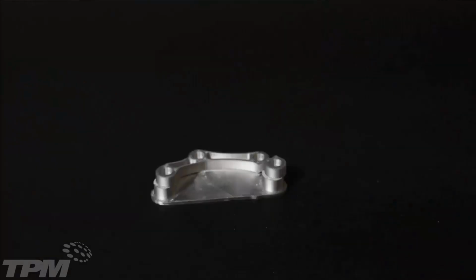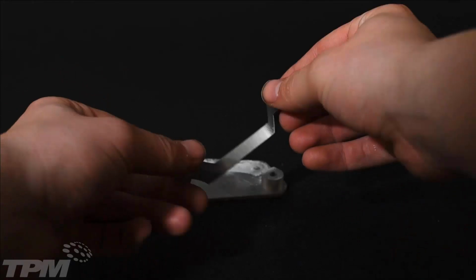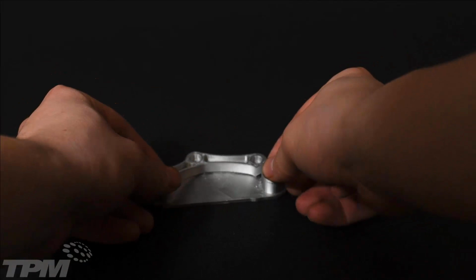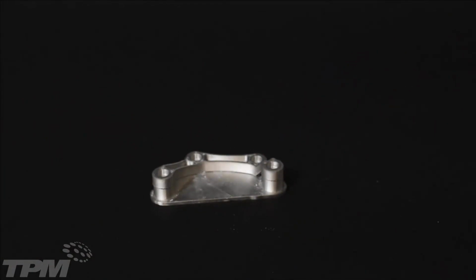And with your finished part, you can see that we actually print on what we call a raft. What that raft does is it helps with the drag forces and uniform shrinkage during sintering. If you place a part onto the setter plate, and as it shrinks, if you have very thin regions, that part may shrink differently than a region that has more material. And as it drags along the setter plate, you may have deformation of your part, or your part may break during sintering. So how we resolve this is printing on a raft that will allow for uniform shrinking.